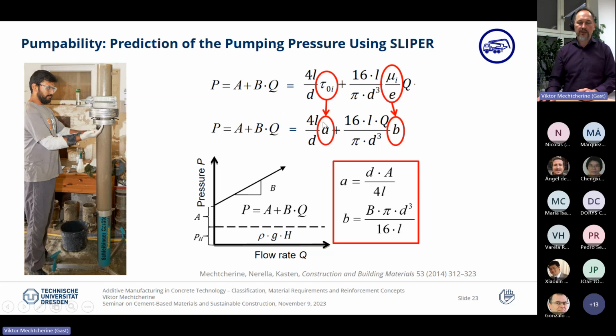And you see from this equation that it takes into consideration the geometry of the pipe, and this is why we have here a diameter and the length, etc. But the major rheological parameters that we use are the yield stress of the lubrication layer, and also the viscosity of the lubrication layer divided by the thickness of the lubrication layer. To make it a little bit simpler, we convert this viscosity divided by the thickness to just a parameter B, a kind of viscosity parameter, and the yield parameter we call A.